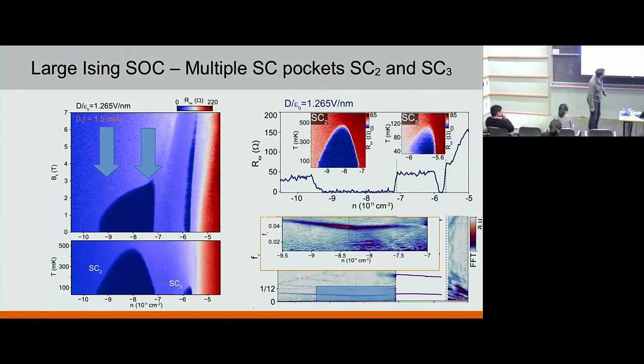And if you have a willing eye, you might see another line connecting from here. It's very vague, so you have to zoom in to hunt for this line. But the idea is that the cross check for all this is you sum up these frequencies and you have to get 1 as an answer, so that you account for the whole Fermi surface. And you stop doing that beyond this point, because if you would want to account for this line, you would have to go down, and it doesn't go down, okay?